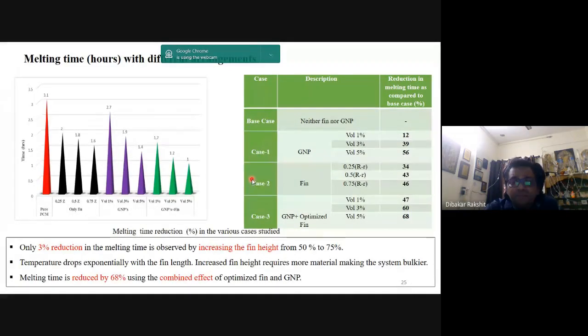So then we started seeing what is the effect beyond which this heat source of the fin can be studied in a way that it is having a positive effect. As I was telling, we introduced graphene nanoplates in different proportions, like 1%, 3%, and 5% by volume, so as to see how much reduction in the melting time, or in the discharging, is happening when we are introducing these graphene nanoplates.